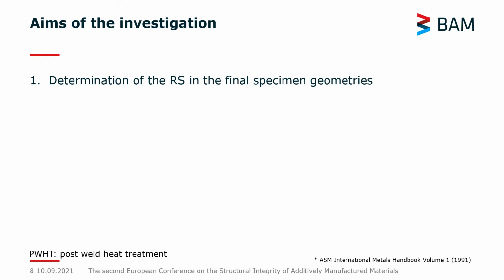So we will determine the residual stresses in final specimen geometries. By final specimen geometry, I mean a specimen that was extracted from this generic as-built shape. So for instance, tensile samples. And we will focus on the residual stress range. So we'll look at the delta between the maximum and minimum residual stress in that specific geometry.